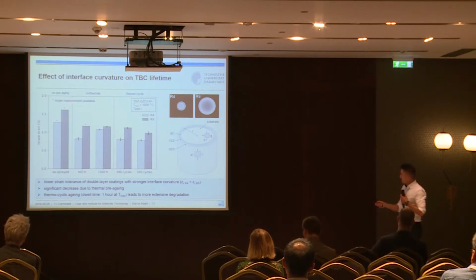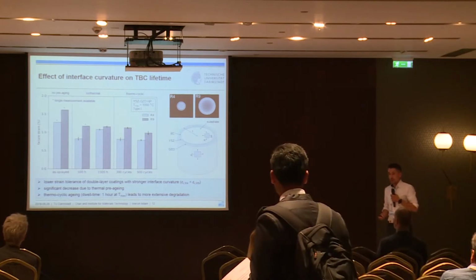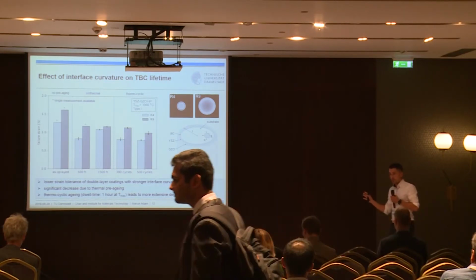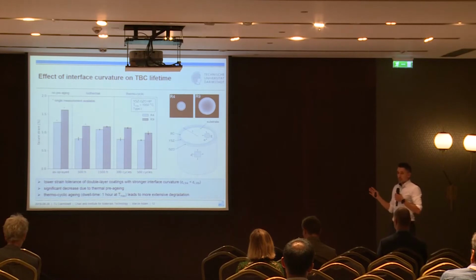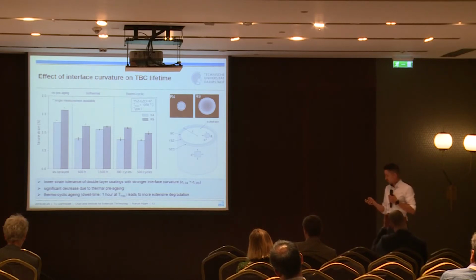And we also find, having looked at the data, a significant decrease due to the thermal pre-aging. What we see is that the thermal aging or the thermal cyclic aging leads to a more extensive degradation of our double layer coating system. And to conclude this slide, all results are in good agreement with previous studies on single layer coatings.